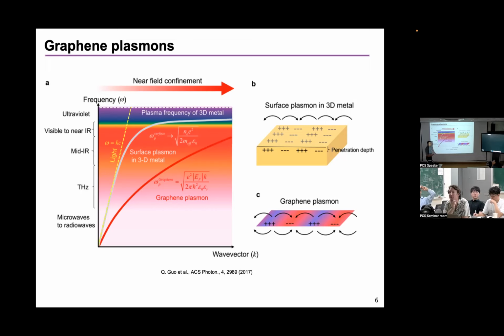Okay. I don't think you necessarily need graphene to be sitting on a 3D surface. You can have suspended graphene, for example, right? Just suspended, with ribbon-like structures drawn in it which can confine, like a resonator, say lambda over 4, or lambda p over 4, and you'll still see plasmon resonance. Yeah. So freestanding graphene can support plasmons, confined into a resonator structure, or if you shine light at non-normal incidence. But still, the role of the metal is played by the graphene structure.